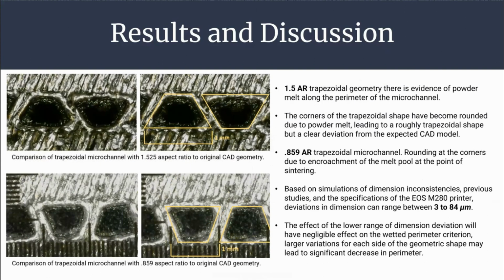Same thing with both the trapezoidal heat exchangers. We can see the largest aspect ratio on the top and the smallest aspect ratio on the bottom here. They're conforming mostly to the trapezoidal shape that we were looking for in the CAD design, but you can see some loss of resolution around the corners as it starts to kind of round off there. And with simulations and based on previous studies, we found that deviations in dimension can range between 3 to 84 microns, which 3 microns is obviously not a big deal, but if every dimension is off by 84 microns, then it's going to lead to a kind of inconsistent wetted perimeter.